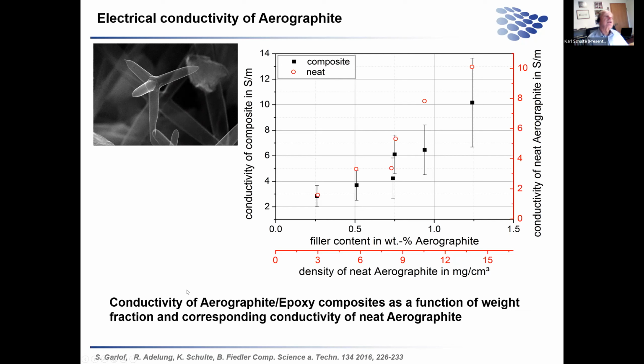You can see here the composite material and the conductivity versus the content of aerographite inside. The red line is just the neat three-dimensional structure, no epoxy inside. With the epoxy inside, we have this black line, which shows an increase in conductivity with increasing content of Aerographite in the matrix.